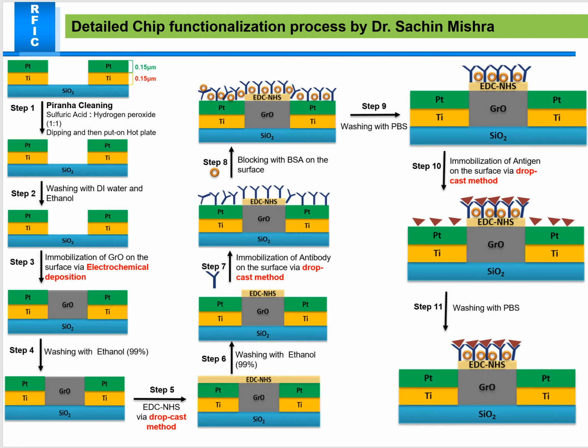Sir, as per your suggestion, I have made this detailed chip functionalization process, and I will use this process in the future as well as today. So the thickness of platinum on titanium is 0.15 micrometer. Then step one is piranha cleaning, and afterwards washing with DI water and ethanol, and then immobilization of graphene oxide via electrochemical deposition.